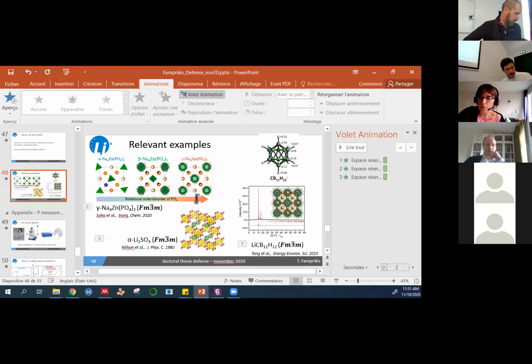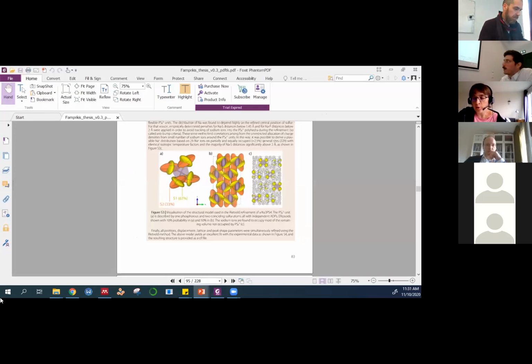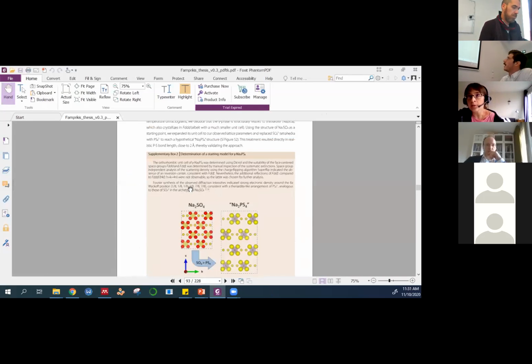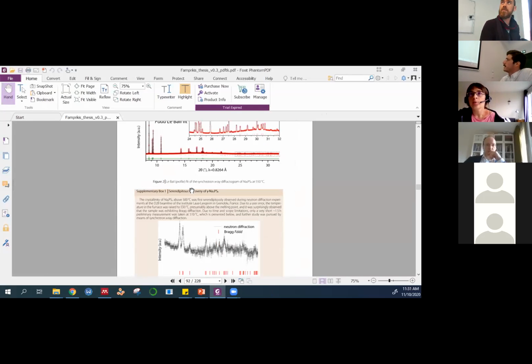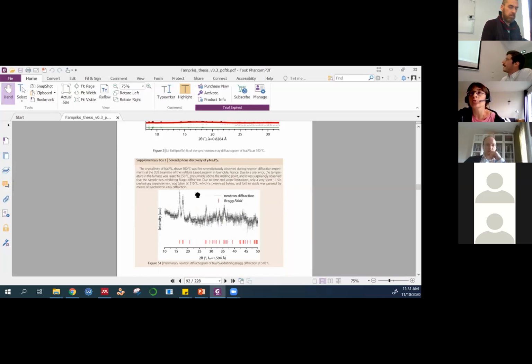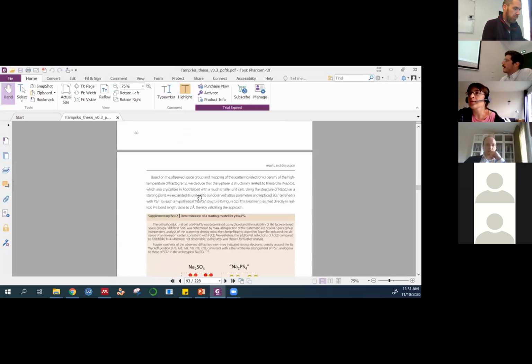Sorry. So going back to the gamma phase, you found it by neutron diffraction. But I saw that the statistics of the neutron pattern was not good enough, and then later you remeasured it on Polaris in the UK. But I was surprised that you only show a profile fit and not a Rietveld fit. Was there some problem doing the Rietveld refinement with neutrons? Why are you showing only a profile matching?